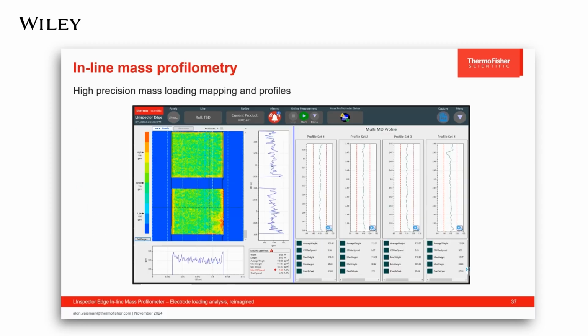The example screenshot here from the mass profilometer HMI shows two patches of NMC cathode. This data was collected at 60 meters per minute line speed. Mass profilometry data makes it easy for the operator to see that the loading is high and out of spec on the bottom right section of the lower patch. A closer look also reveals what appears to be a streak in the machine direction, in the vertical direction. The software is able to calculate statistical variables like average, maximum, and minimum loading in grams per square meter, and transmit this information in real time to the plant control system.